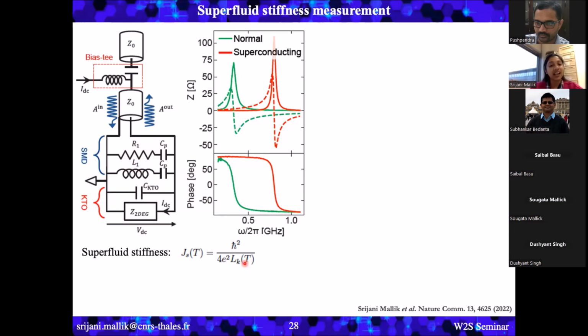So basically, when we measure it at the normal state, we find this resonance, and when we measure it at the superconducting state, due to the appearance of this extra kinetic inductance, there is a shift in the resonance frequency to the higher frequency side, and also there is a phase shift. So from this, we can calculate this kinetic inductance of the 2DEG and finally calculate the superfluid stiffness.